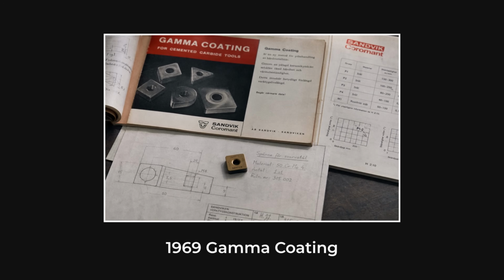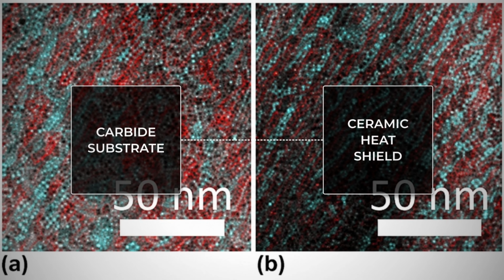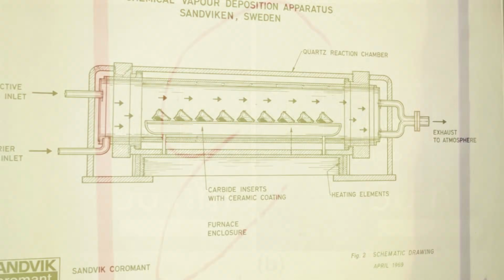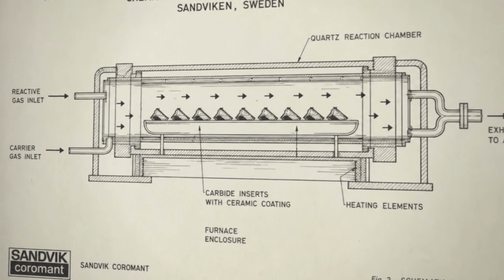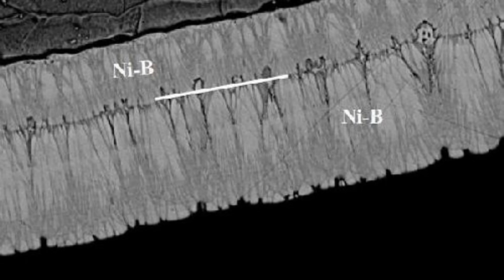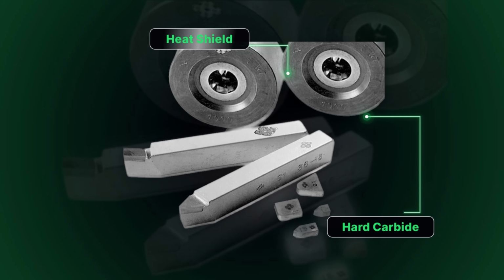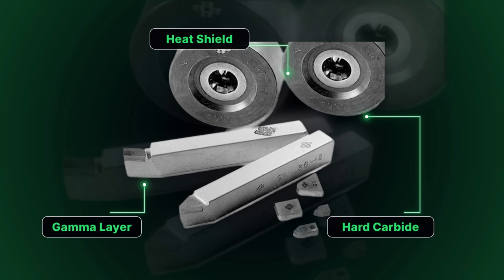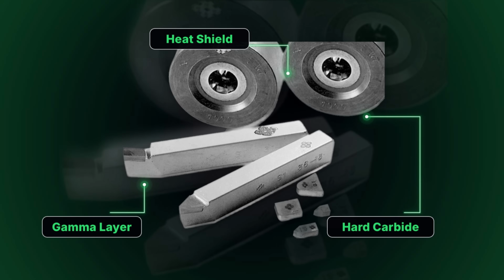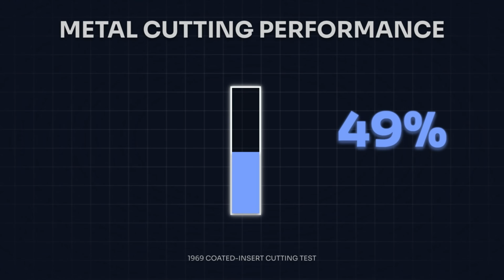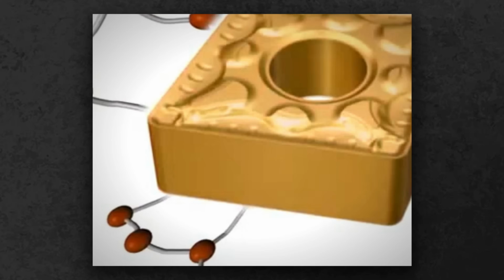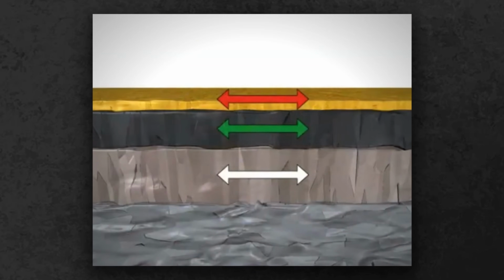In 1969, the company introduced gamma coating, the first surface-coated cemented carbide insert in the world. A microscopically thin ceramic layer was deposited onto the carbide substrate by chemical vapor deposition, gas reacting on the hot surface and building up a film measured in microns. The substrate underneath stayed tough. The skin on top was ceramic hard and thermally resistant, so heat that used to soak into the carbide got kept out of it. Metal cutting performance jumped by as much as 50%. Every coated insert made anywhere in the world today, by any manufacturer, descends from that.